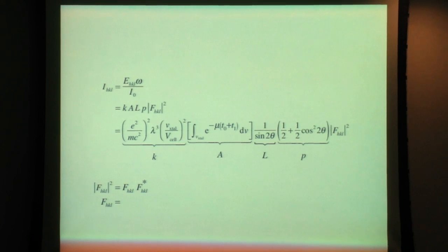So because of the volume of the reciprocal lattice point and the thickness of the Ewald sphere, there is this factor, which in the simplest case is just 1 over the sine of the scattering angle. In other geometries, more trigonometric functions enter, but it's all just dependent on scattering angle. And then here's the polarization factor that J.J. Thomson worked out long ago.